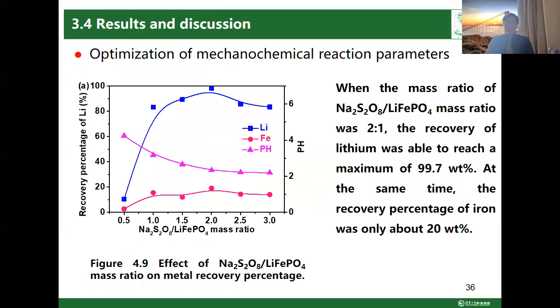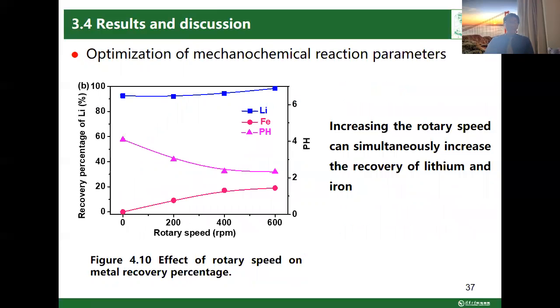This figure shows the effect of different material mass ratios on metal recovery. When the mass ratio of this material is 2:1, the recovery of lithium was able to reach the maximum. At the same time, the recovery percentage of iron is only 20%. The result in this figure shows that increasing the rotary speed can simultaneously increase the recovery of lithium and iron, but the effect on iron was significantly higher than that for the lithium.